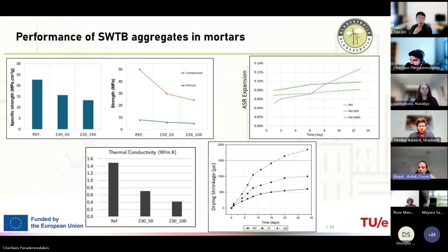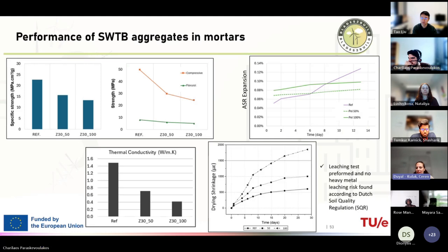Also, from the physical properties, we have checked the thermal conductivity because we are bringing some closed pores inside the mortar. And we see improvement in thermal conductivity, so it has an insulation property. And if you click one more, please. We also have checked the leaching according to the Dutch soil quality regulations, and we didn't see any risk on the leaching properties. Yes, if you click one more, Haris. We have tested one batch leaching and there was no risk.